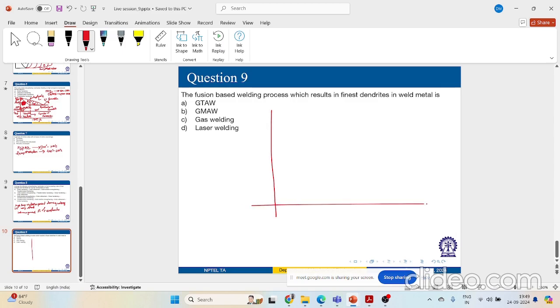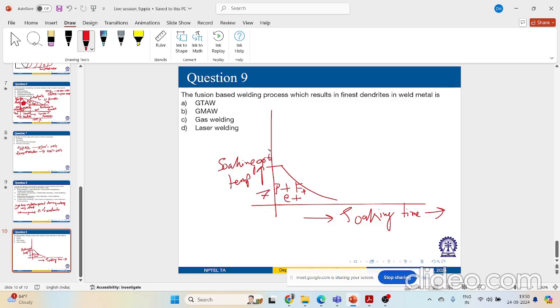So this is my soaking time and this is my soaking temperature, right? So over here, this will be pearlite, ferrite, cementite, and not austenite over here. So this is in the temperature range of 900 to 700 I'm talking about. Fine.